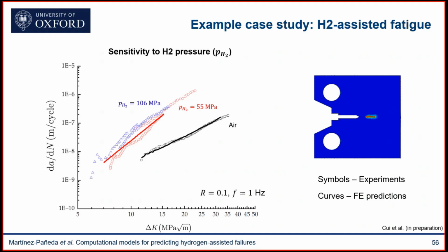And then they also have data for 106 megapascals, so higher hydrogen pressure. So again, I change the pressure, the hydrogen content in my model. Again, I don't touch any of the parameters of the model. This is a completely blind prediction. Again, a very good agreement.